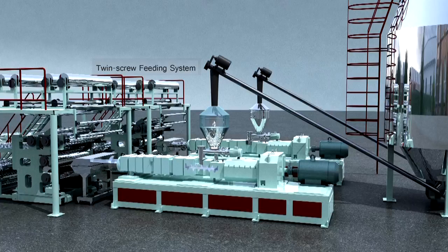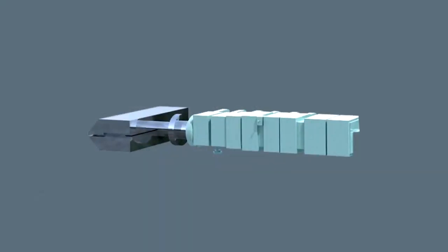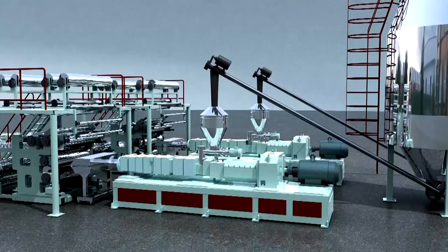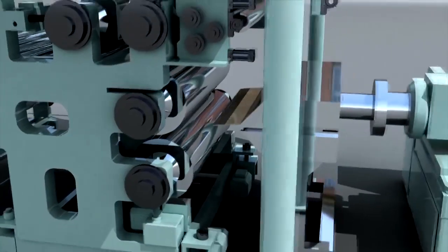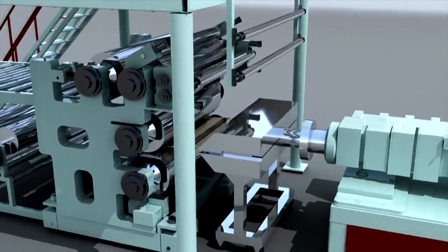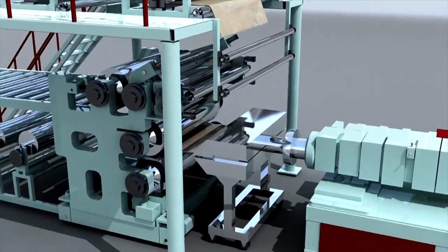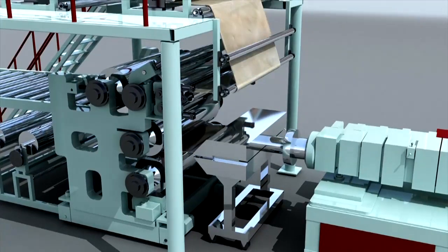Then the twin-screw feeding system evenly transports the material to the extrusion system, and after heating and plasticizing, temperature control is the most critical link in the process. The heating and heat dissipating output is controlled by the temperature control module, and the high-precision K-type thermocouple temperature measurement completes temperature control. After the material is heated to melt, it is rotated by the screw to generate a strong pressure and then extruded into the mold. The product specifications are determined by the size of the mold.